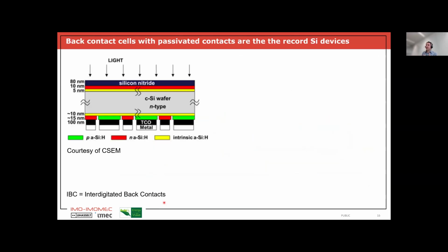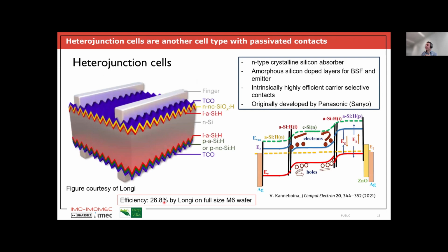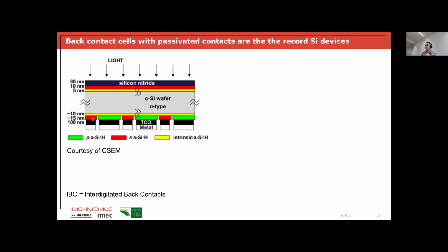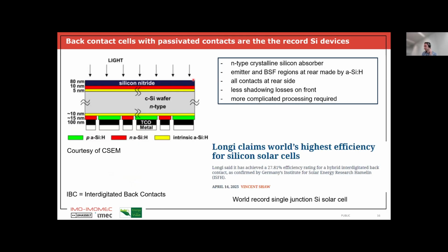But there is already a next generation being prepared. These are so-called back contact cells. So in the previous cell structures, we still have always a contact at the front and the rear of the device. So on both sides, you have one contact, one polarity. This is the traditional way. But we can also put all the contacts on the back side. That's why it's called a back contact cell. And that has as the advantage that you don't have shadow losses at the front, and you can typically still go slightly higher in efficiency.